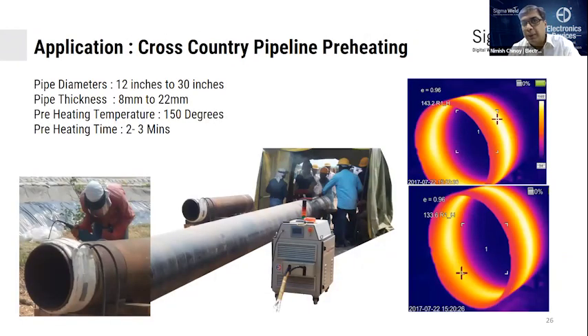This is for cross-country pipelines. Just to show you this thermograph on your right, you can see there are 2 temperatures taken within a span of 10 seconds. So it is 15:20:26, and this is 15:20:30. There's hardly 4 seconds difference between the temperature on the outside and inside. And you can see the temperature achieved is 143 degrees here and 133 degrees here. That means the delta T is less than 10 degrees between a 15 thick pipe on the OD and ID.